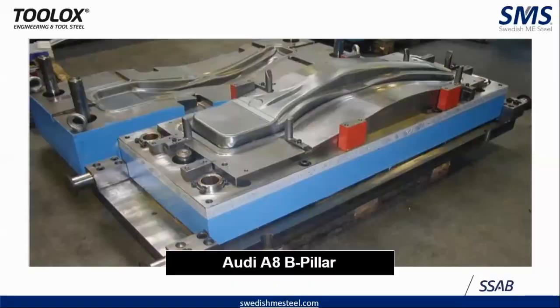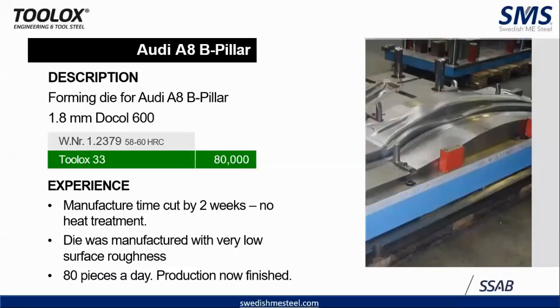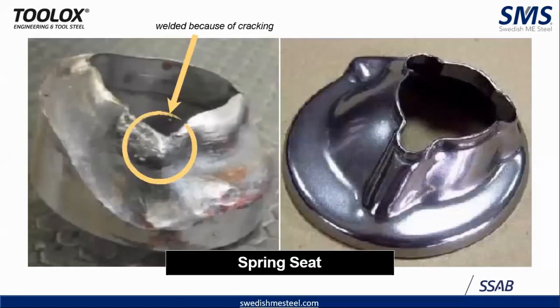This is an Audi A8 B pillar. The sheet metal thickness was 1.8 mm. It was Docol 600 MPa sheet. The previous metal was D2 at 60 HRC. They were able to reduce the manufacturing time by 2 weeks. No heat treatment is required. The die was manufactured with low surface roughness. Being in a high-end car, the production level is very low, 80 pieces a day. The spring seats are the areas where you will face issues of cracking. Thanks to the toughness of Toolox 33, you are able to address that.